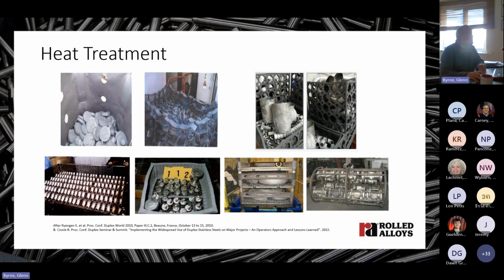Now, in this slide, if you look on the top row, we see small weld neck flange forgings and butt weld fittings and some larger butt weld fittings packed into baskets ready for heat treatment. But the problem is, because of how the parts are packed into these baskets, the free flow of hot air between and through the parts during heat treatment is restricted. The efficiency of the water quench is going to be equally restricted. So parts on the periphery of the load may be okay, and if they're tested, they may pass. But parts in the middle of a load may well be metallurgically defective.